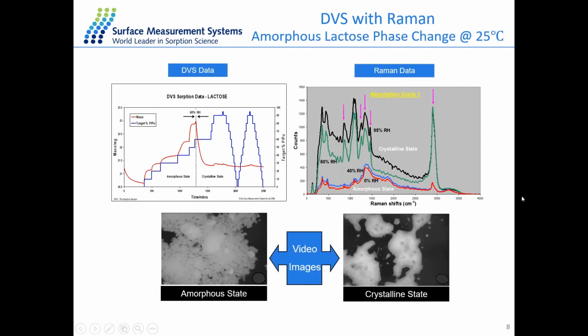And another accessory that can be integrated with the system is Raman spectroscopy. So inside the DVS chamber, we have a port for the Raman probe, and we can take the Raman spectra at the end of each humidity step. So on the left-hand side, here's an example with the amorphous lactose sample at 25 degrees. And on the left-hand side, we have the DVS data for the moisture sorption, where we change the humidity, which is the blue line here on the right hand. So the humidity changes from 0 to 90 or 95% RH with 10% intervals. And the red line is the change of mass for the sample.